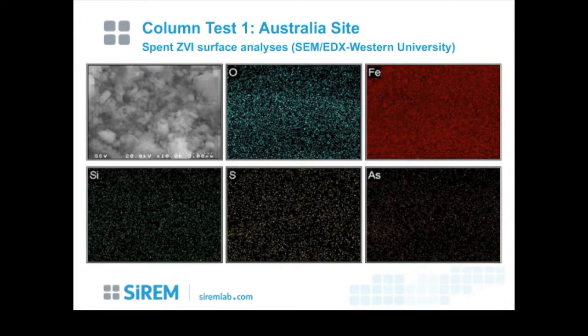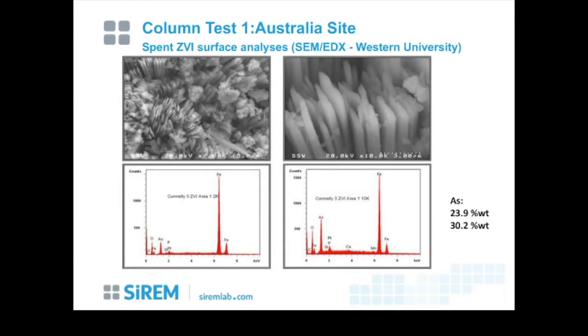I'm not going to go through all these results, but this technology was used, scanning electron microscopy with an energy dispersive X-ray, and we used this to help understand where the arsenic went and how stable it was. Essentially, it shows the arsenic absorbed onto iron oxide surfaces, and it was uniformly distributed. I'm not the expert in interpreting these ones. We used a local university, the University of Western Ontario, to help us interpret these results. And this next slide here is the same technology, just a higher magnification, 2000X and then 10,000X left and right.